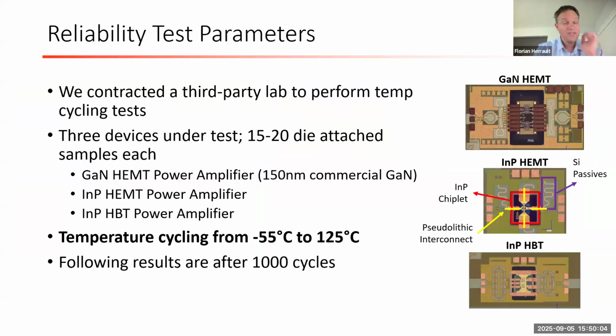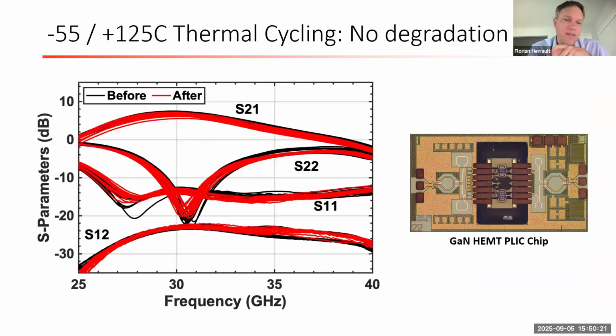And then similarly, early data on reliability have been very positive. I picked one of the reliability tests we've done, thermal cycling, using a mil standard across 3 different chiplet technologies, GaN, indium phosphide HEMT, and HBTs. And on this slide, you're seeing results after 1,000 cycles, which if you've not done it, this is several months at the third-party vendor where chips are mounted on a die attach carrier and cycled through their ovens, again, per mil standards. And what we show here is effectively no visual and electrical degradation after those 1,000 cycles. So very positive early results, much more work to do, obviously, as we increase the number of chiplets per chip, etc., but at least no showstopper in the short term.